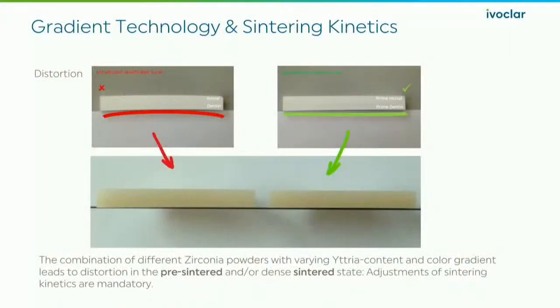So what you see on the left is a slice that was not with the gradient. You can see you start to get a little bit of warpage. The black line at the bottom shows it's pretty relevant. Up at the top, to the left side of that, is the translucent portion, and it's being pulled away because it's taking longer to sinter, so it's kind of slumping off there a little bit.